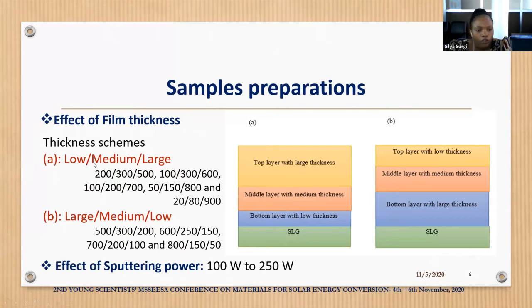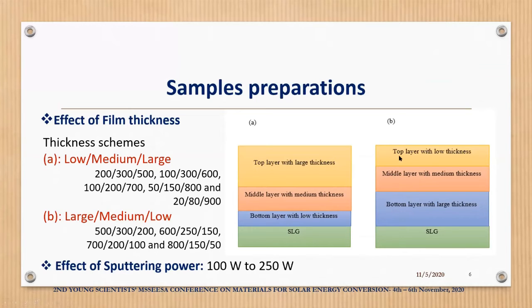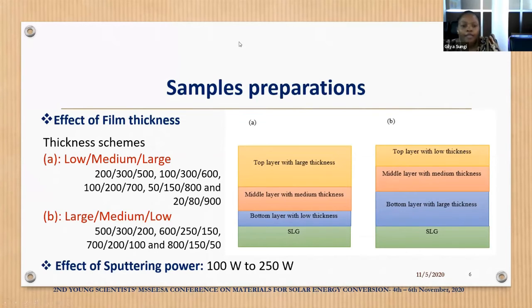The first one is called low, medium, large, which means we have a low bottom layer, medium middle layer, and large top layer. That is scheme 1. And scheme 2 is large, medium, and low, which means we have a larger bottom layer, medium middle layer, and low top layer. The choice of these thickness schemes was selected to investigate the problem of peeling off.